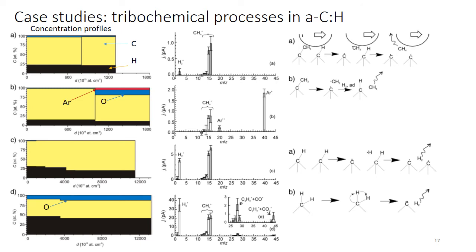It was concluded that the generation of these gases should be by bond breaking due to shearing, and recombination of the radicals with hydrogen or CH molecules, which give rise to emission